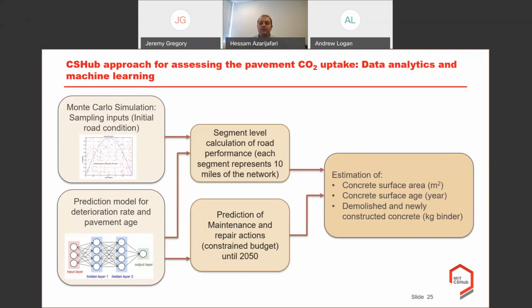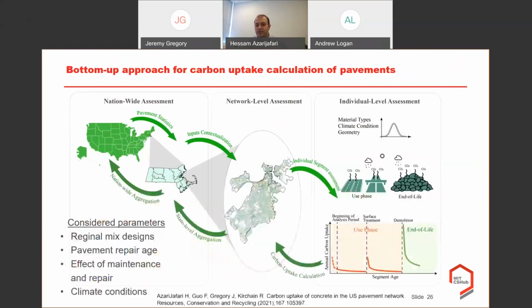And based on that, we had a good estimation of the concrete surface area, the square meter area that I discussed in the equations, the concrete surface age, at what age the concrete segment is currently, and the demolished and newly constructed concrete volume, so we can have a good estimation of the kilogram binder in different locations. So this bottom-up approach of the carbon uptake calculation will start from the pavement statistics, the input contextualization here. Then we have the individual segment assessments, and once we calculate the uptake during the usage and end of life, we will aggregate the results at the state level and the nationwide level.